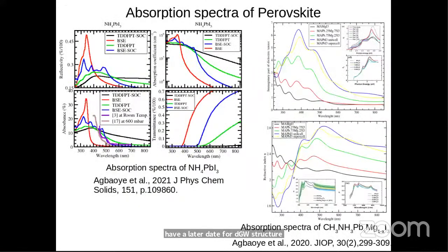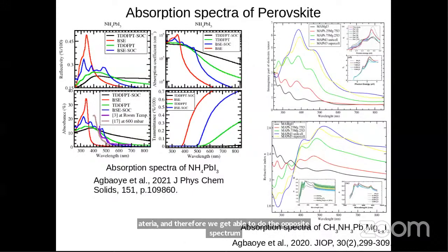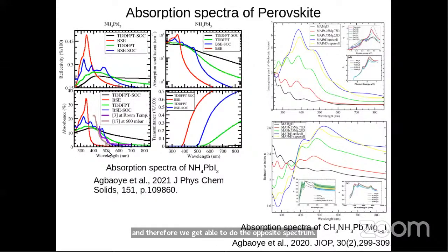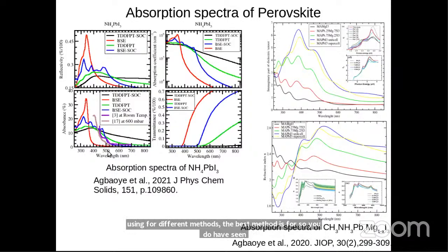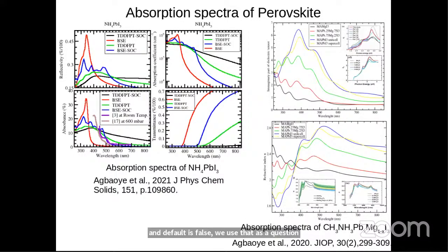And then we are also interested in looking at the absorption spectra of perovskite material. And for methylammonium lead iodide, we are able to do the optical absorption spectra. And here we have the result of absorbance using 4 different methods. The first method is for us to use TDDFT with spin-orbit coupling. The second method is to use the Bethe-Salpeter equation without spin-orbit coupling. The third is to use only TDDFT without spin-orbit coupling. And the fourth is for us to use the Bethe-Salpeter equation with spin-orbit coupling.